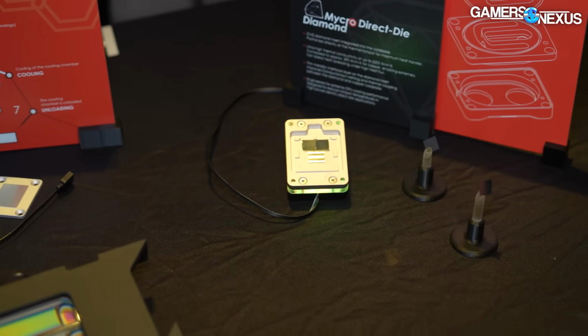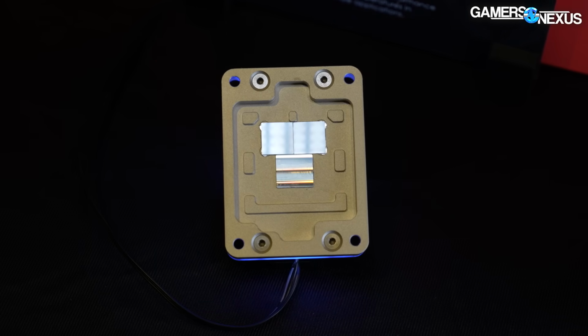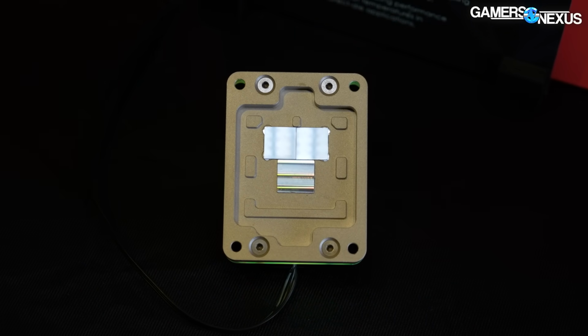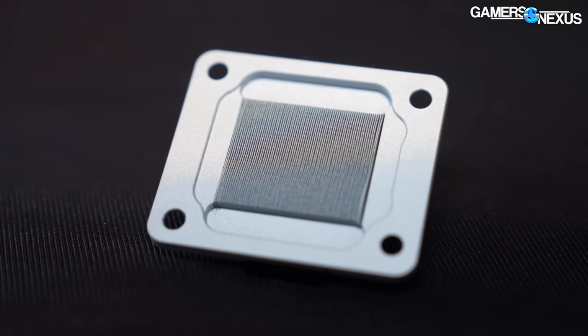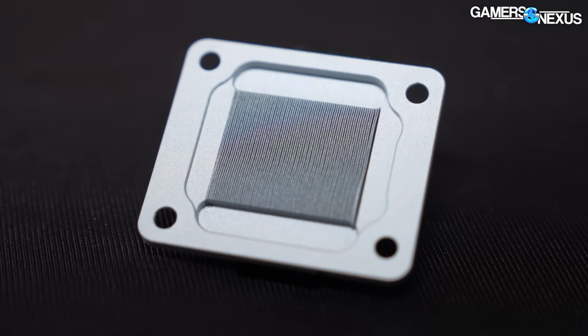Okay. So what is this, and why diamond? For direct die cooling, when it comes to performance, we are just limited by how much fin density we can pack into the block. The power density of the chips is very high these days, and we can't really improve it further from the engineering perspective on how we make the block. You can find half a degree here and there, which is a lot. Yeah, in the water cooling space, if you can get 1 degree, I feel like that's a lot at this point.